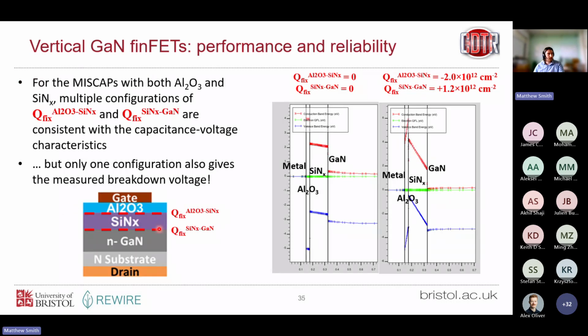For this structure, we have 2 interfaces, so we've got 2 parameters to play with here. It turns out we can have lots of configurations of these 2 fixed charge numbers that give us results consistent with our flat band capacitance, but only one configuration that's consistent with both our breakdown voltage and our flat band voltage, and that's this configuration here where we have negative charge at this interface and positive charge at this interface. What that's actually doing is introducing an electric field inside our dielectrics.